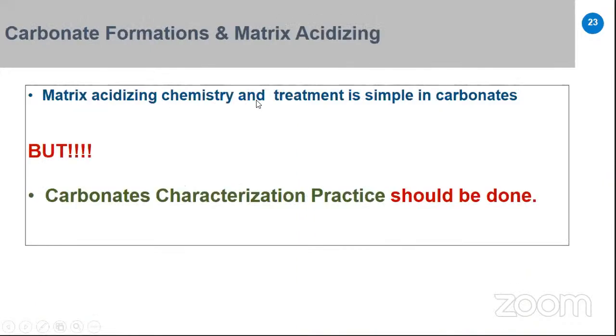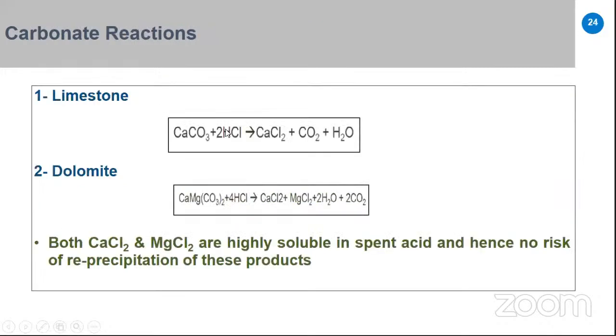Matrix acidizing chemistry is understandable and simple in carbonate, but usually we need to do characterization for the carbonate to select the best treatment. So usually this is the carbonate reaction with limestone. This is the chemical formula for the reaction. Calcium carbonate reacts with HCl, producing calcium chloride as a salt, plus CO2 plus H2O. Dolomite reacts with HCl and gives products like calcium chloride, magnesium chloride, water H2O, and CO2. And the advantage of this reaction is that both CaCl2 and magnesium chloride are soluble in the spent acid, and there is no risk of reprecipitation of these products, as with sandstone secondary and tertiary reactions.